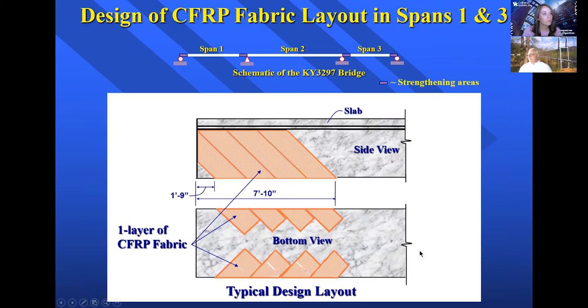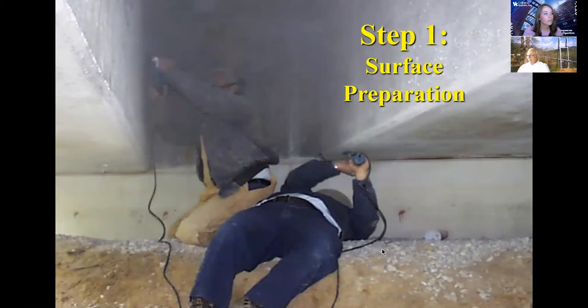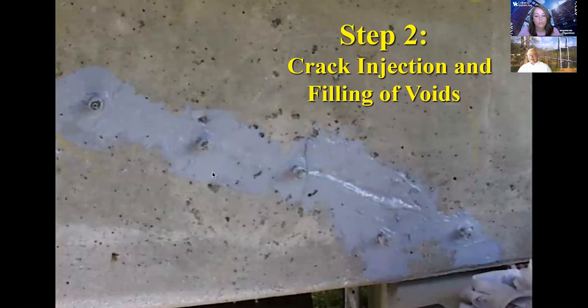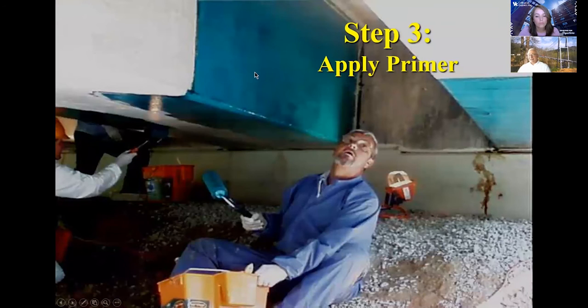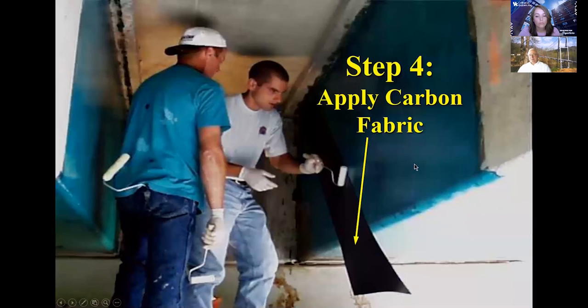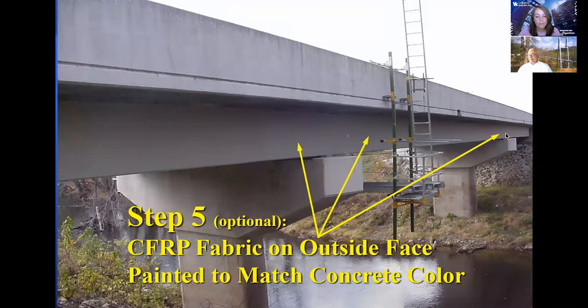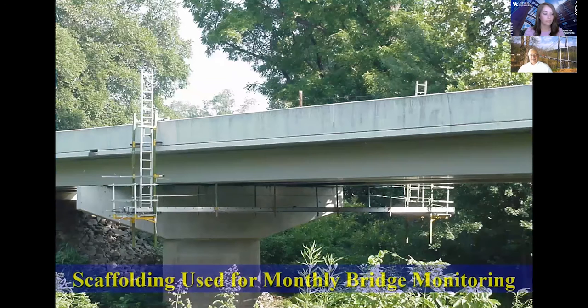Now, carbon fiber is very expensive, so we want to optimize its use as much as possible. The way you apply carbon fiber fabric is just like you're applying wallpaper. You start by cleaning the surface, and if there are any cracks, we inject the cracks, and then we fill any void on the surface. Then we apply a primer. Then we roll the fabric on, and actually you just roll it with a roller. It's very thin. This was very thin fabric at the time, and was the best that you could get. After we finished, we painted the outside, so people would not be looking at the black fabric in there.